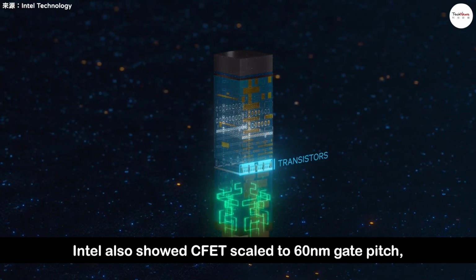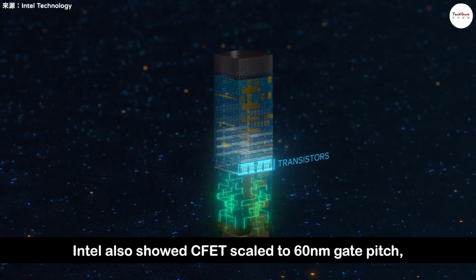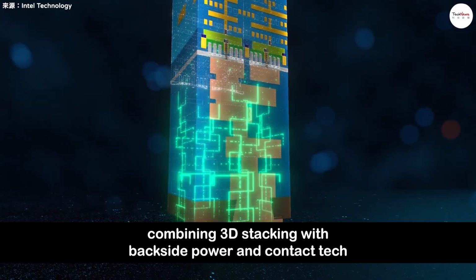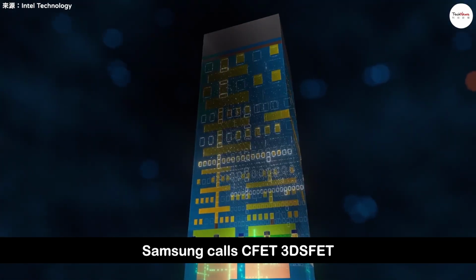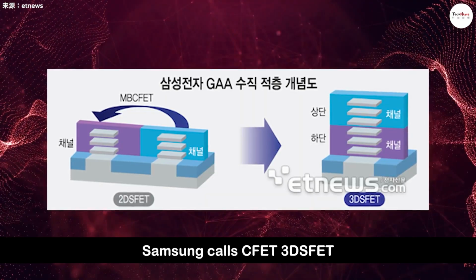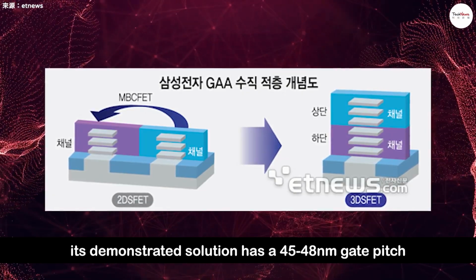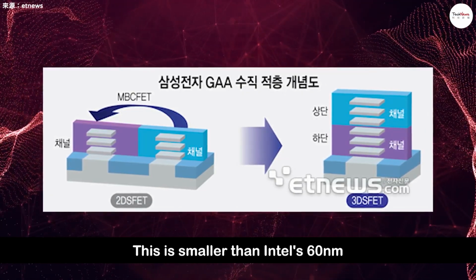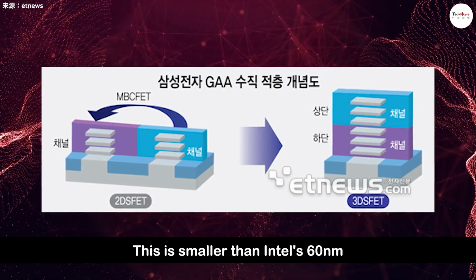Intel also showed CFET scaled to 60 nanometer gate pitch, combining 3D stacking with backside power and contact tech. Samsung calls CFET 3DSFET. Its demonstrated solution has a 45 to 48 nanometer gate pitch. This is smaller than Intel's 60 nanometers.